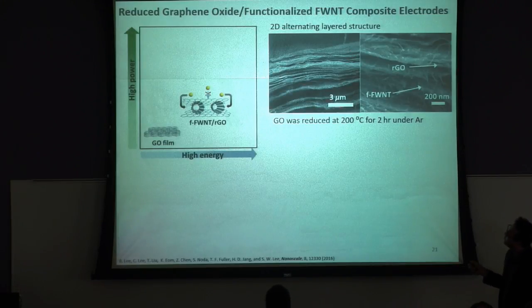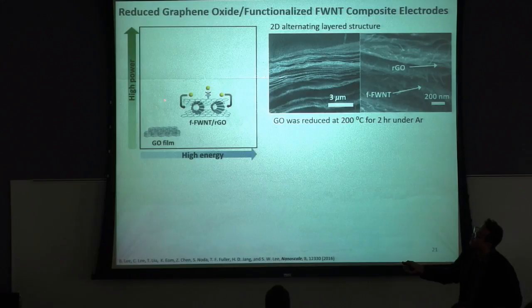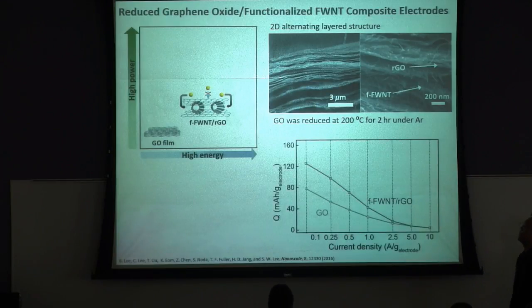So now, to recover the electrical conductivity of graphene oxide, we partially reduce this graphene oxide at 200 Celsius for 2 hours under an argon environment. Then we can expect some kind of fast ion diffusion through the gaps between the graphene oxide. If we compare charge storage performance, at the slow current density the capacity has been increased from 80 to 120, right? Also, if we increase the current density, we can actually get better rate performance, right?